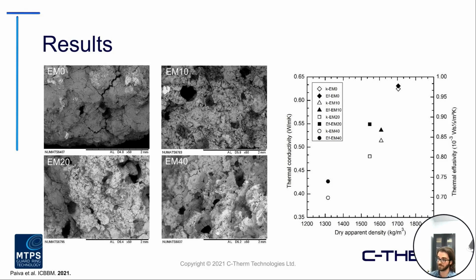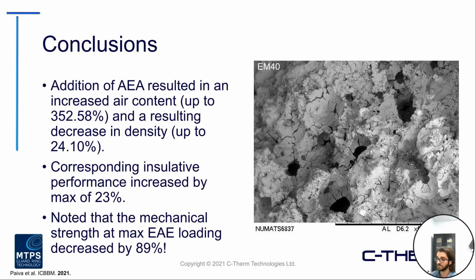But from a thermal aspect, at least, we can see that going from the top right, which was the earth mortar with no AEA additive, all the way down to the highest concentration in the bottom left, you do get a noted decrease in both conductivity as well as effusivity, trending in the same way. So in conclusion, they were able to use this AEA in this earth mortar mix to increase the air content by quite a significant degree, with a corresponding net decrease in density. This all added into improved insulative performance, increasing by upwards of 23%. Again, increasing insulation performance means decreasing conductivity values.